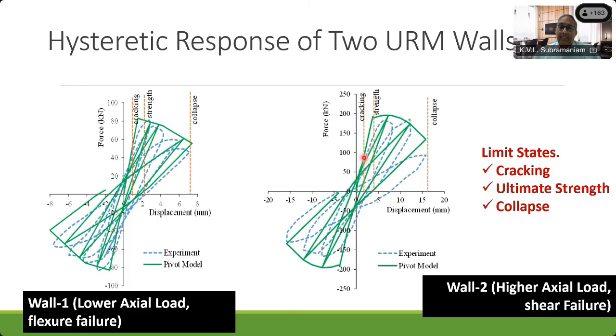Now, the limit states are identified from the model. One is that of cracking. That comes from the envelope curve. This is the envelope curve. So the masonry cracks here. This is identified as a strength state, maximum stress. And this is the collapse where the masonry fails. So these are the 3 limit states that we have. Cracking happens very early in the response. Then you have the strength, which is the maximum resistance, and then collapse, where it fails. And after that, there's no more load resistance.